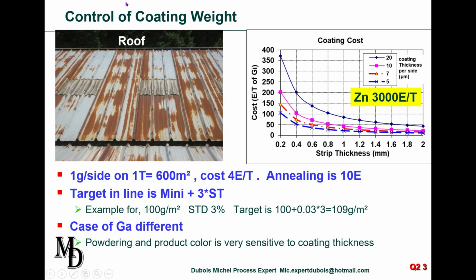On this typical picture, we can see that the coating weight was varying along the sheet, which typically refers to a strip vibration issue, and that's because the coating was not uniform. It was much lower where the steel is already rusted. But on the opposite side, of course, zinc coating has a significant cost.